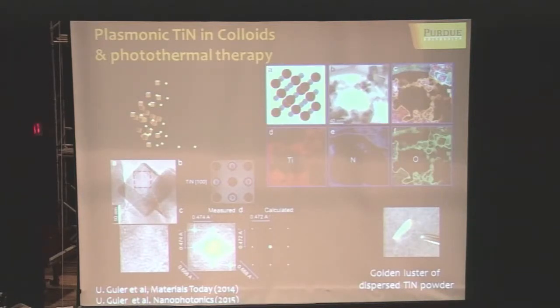You just take simple titanium particles, which cost next to nothing, very cheap, and you could take them of any size, and you anneal them in the atmosphere of ammonia. So basically you replace oxygen with nitrogen, and you get these beautiful titanium nitride particles.